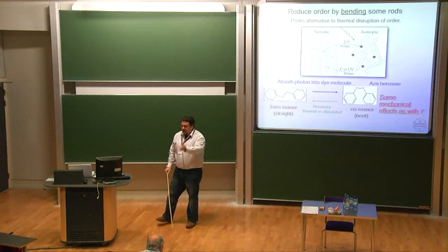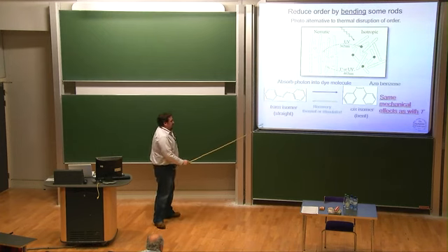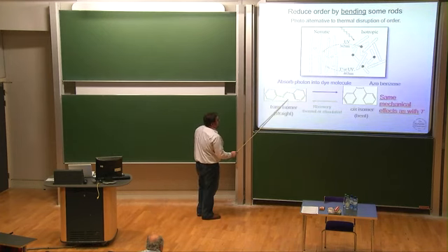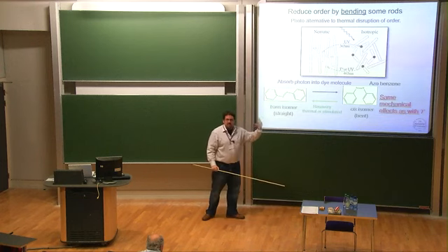So you can shine light in a system and lower the order parameter. You can get back to the original state, the ground state of the molecule, just by waiting, just a regular old recovery, or you can stimulate it with the right other wavelength of light, stimulated emission. So this is the primary coupling. I should point out that there are other, better molecules out there floating around.